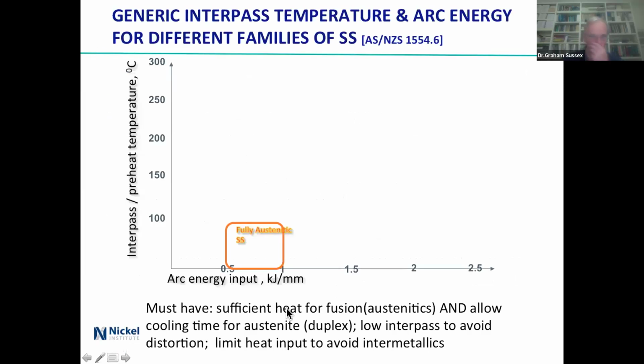So this is a diagram I swiped from AS/NZS 1554. Oops, sorry, it's AS 1554 Part 6 these days. Arc energy input against interpass preheat temperatures. So for a fully austenitic, something that's going to crack if you even blink at it, keep the temperature down, 0.5 to 1. You've got to have enough for fusion, obviously.